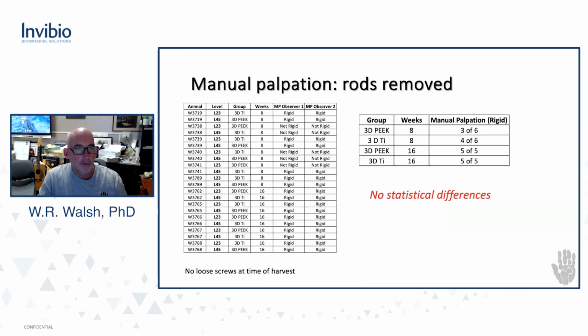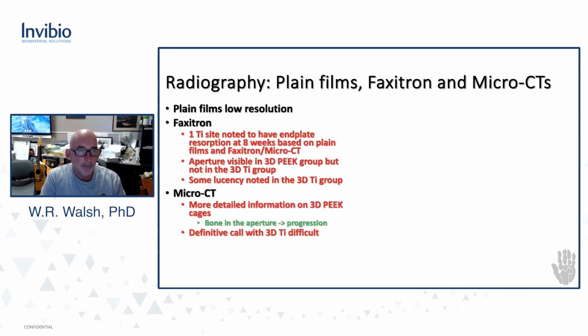If we look at the results, we did manual palpation after we euthanized the animals. We removed the rods, and we did manual palpation. There was no statistical difference between PEEK, 3D PEEK, or 3D titanium. They both supported the fusion of the spine at 16 weeks, and they both were progressing at 8 weeks.